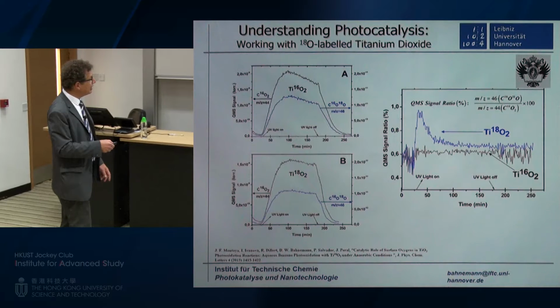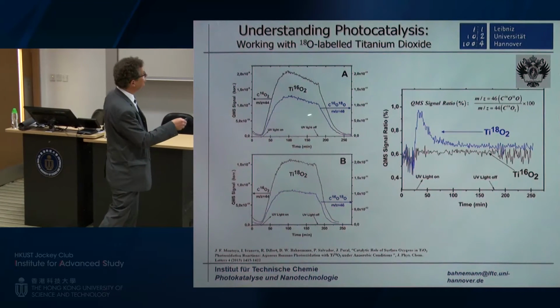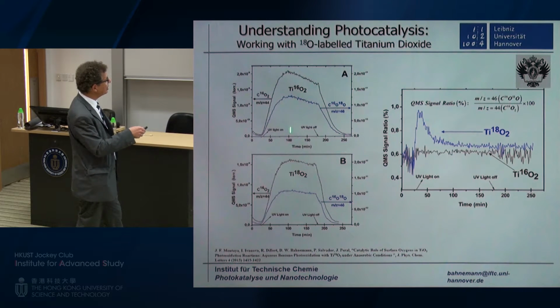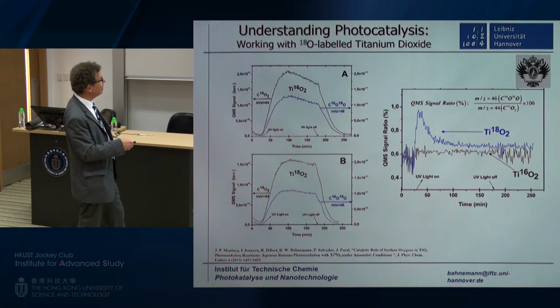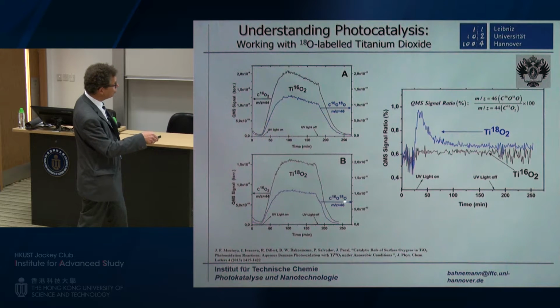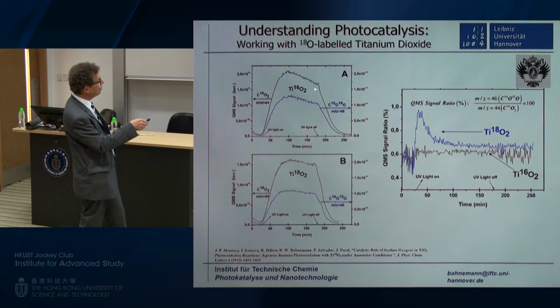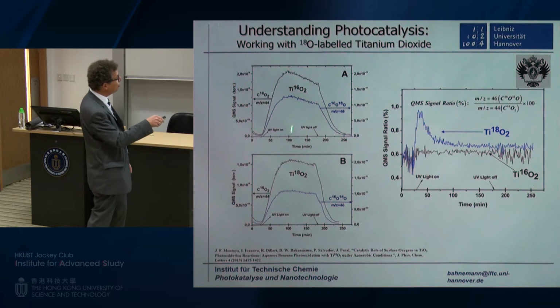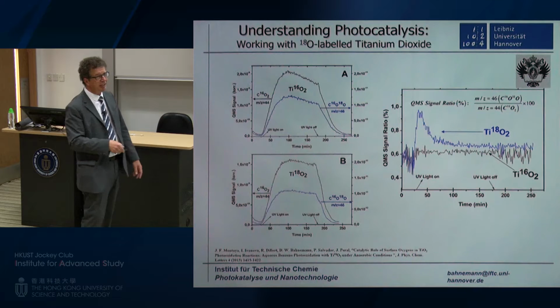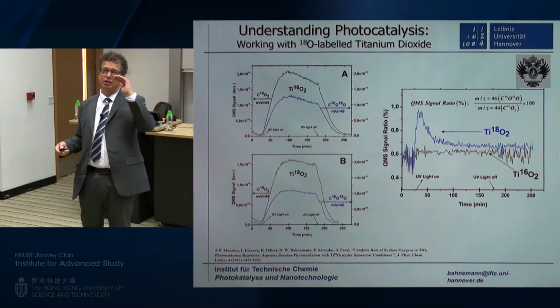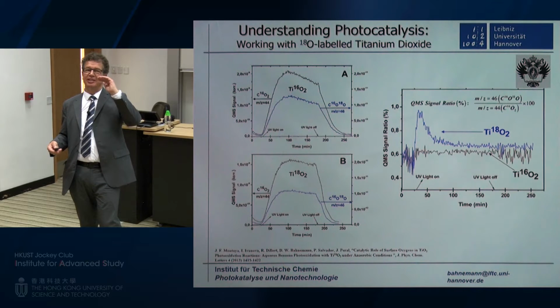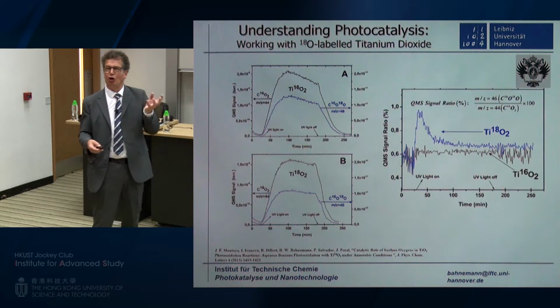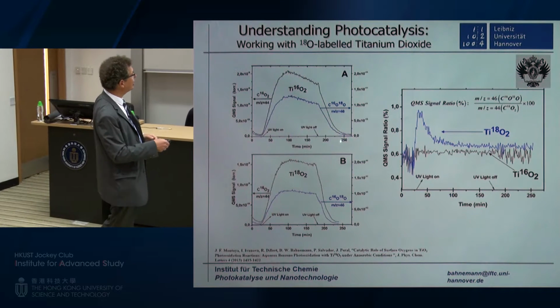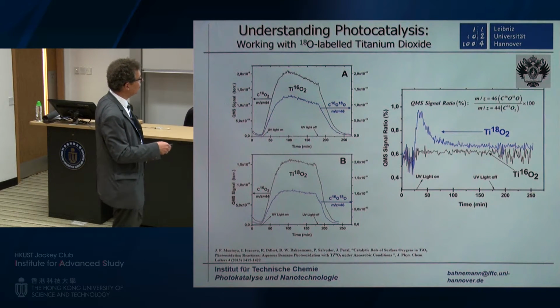And we did this with normal TiO2, with the usual TiO2 with O16, and with the O18 labeled TiO2. The blue curve shows you the mixed oxides, the CO2 with O16 and O18, and the black curve shows you the normal CO2 with O16s. And you see in both cases you get some CO2 with O18. This is what you expect. There is a natural amount of O18 in the water already. You always buy some O18. Not a lot, but you buy some, and you see this scale is much smaller than the other scale.